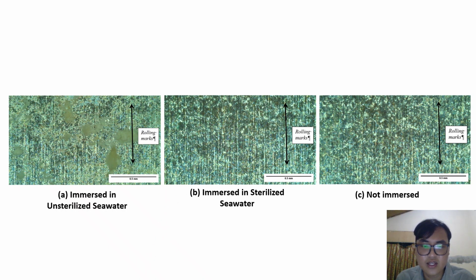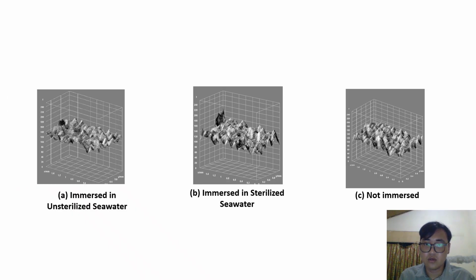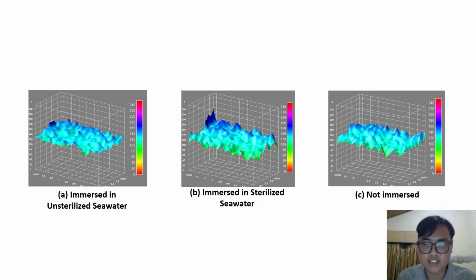However, the damage here was structural. Without biofilm protection, the surface suffered from a stable pitting corrosion driven by chloride ions. These pits became deep and autocatalytic, leading to severe material loss by the 5th month. This is the same image plotted as a surface plot with the help of ImageJ software. This is the same image that is colored. On the right of each image, you can see the scale to easily identify the data from the color of the image.